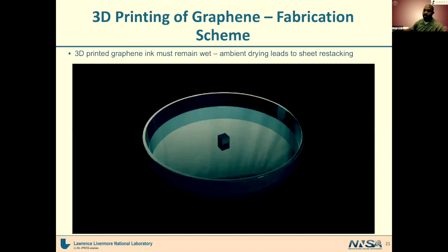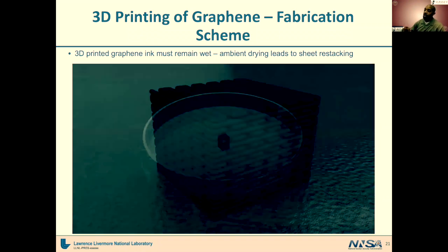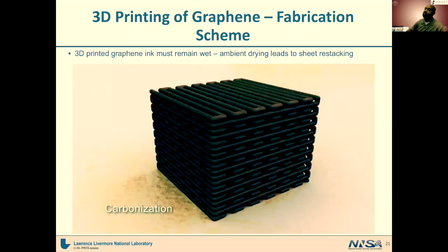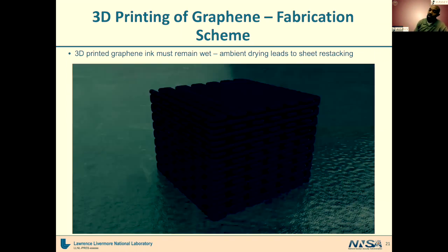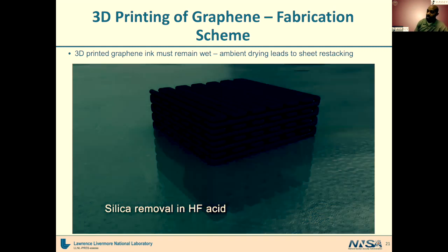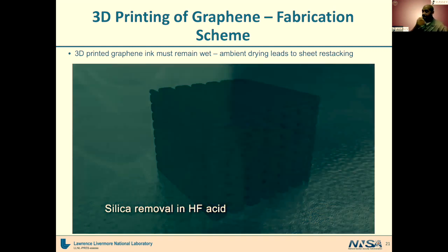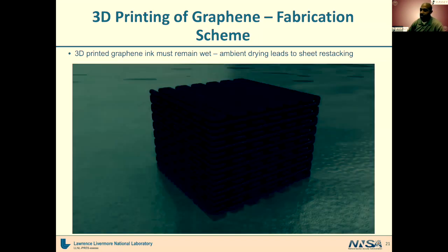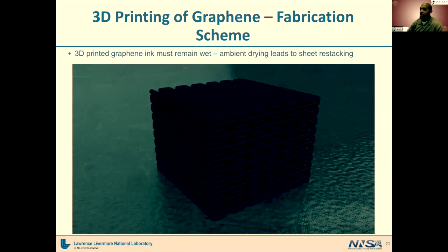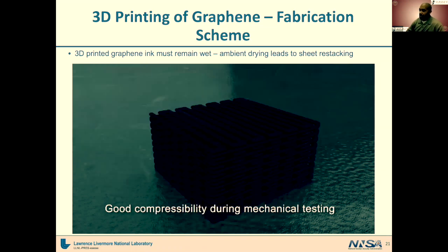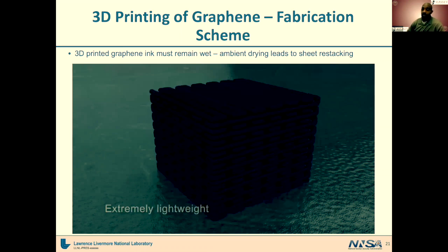So we can take it through the regular process for gelation, drying, and carbonization. Because if we decide to use silica in there, we don't want that in the final material. We can remove that using an acid etch. So shown here, exposed to HF acid, hydrofluoric acid, you can remove it. And then dry your material, and you now have a material that has low electrical resistivity and is also fairly compliant, and is basically the properties that we'd expect to have from an aerogel.